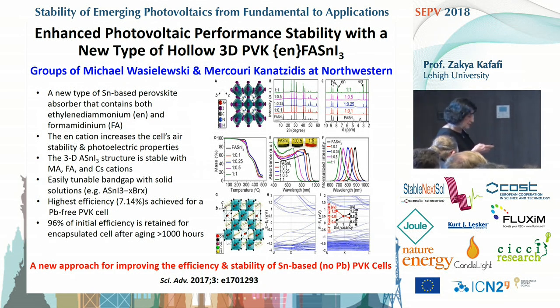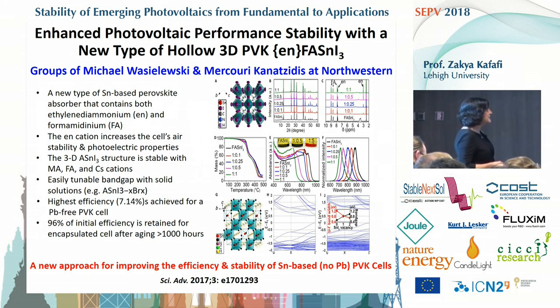Another interesting type of materials was developed and studied by the group of Mercouri Kanatzidis and Michael Wasielewski at Northwestern. It's a new type of lead-free tin-based perovskite absorbers that contain both ethylenediammonium and formamidinium. So the cation increases the air stability and photoelectric property. And this 3D structure was shown to be stable with methylammonium, formamidinium, and cesium cations.